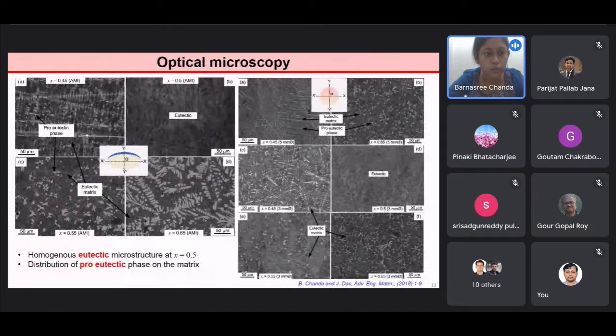Optical microscopy, A, B, C, D, shows the arc melted ingot, where we see the pro-eutectic distribution over a matrix at 0.45, 0.55, and 0.65. But at 0.5, there is no evidence or any trace of pro-eutectic. Similar results can be seen in the suction casted rod, where except at 0.5 there is the presence of pro-eutectic phases.